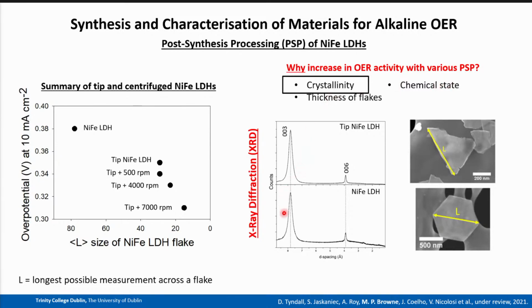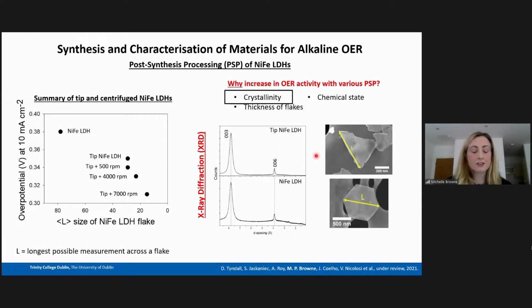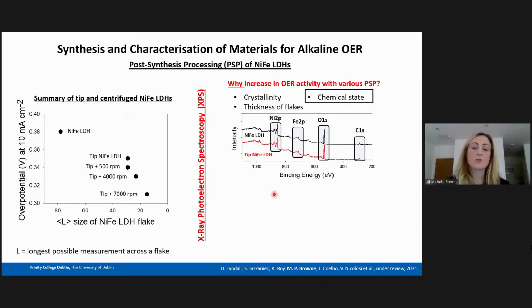And by looking at the XRD patterns, essentially the reflection peaks are the same. Positions have not changed. So we could rule out any changes in crystallinity for any increase in OER activity of our materials. Second, we also then wanted to look at any chemical changes or any introduction of any defect materials.